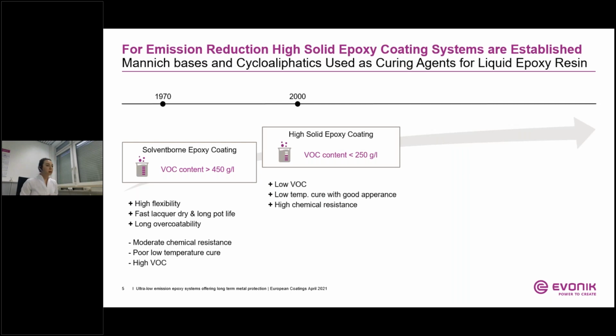So what happened then is that at the beginning of 2000, maximum VOC limits in coating applications were introduced. Then the development work moved away from traditional solvent-borne coatings to high solids, with the target to reduce emission levels. When formulating at high solids, the most significant change is the replacement of high molecular weight polymers by low molecular weight alternatives, which naturally have lower viscosity. Typically, for high solid coatings, Mannich bases or cycloaliphatics are used as a curing agent along with liquid epoxy resin, which enables the formulator to achieve VOC content lower than 250 grams per liter.